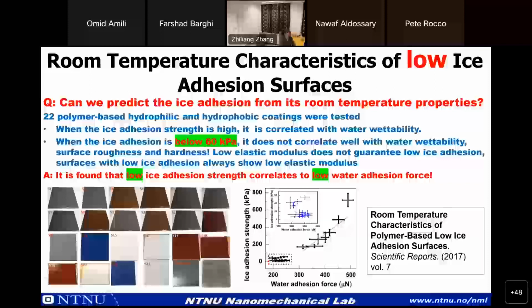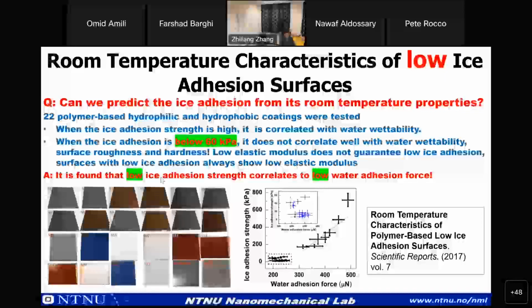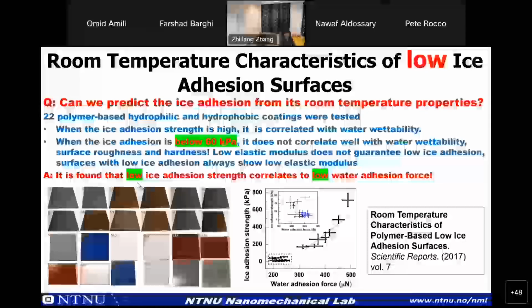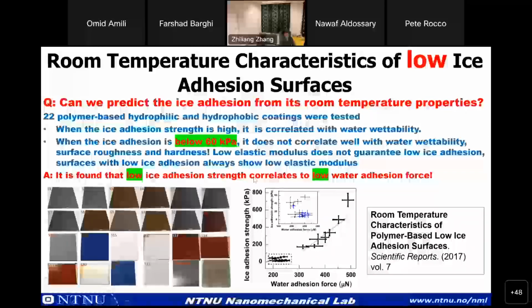What we found is that when the ice adhesion is below 60 kilopascal, there is a kind of correlation between the ice adhesion strength and the water adhesion force. Here we see this is below 60 ice adhesion, and in this region, the water adhesion is very low. So I will talk about the correlation more.